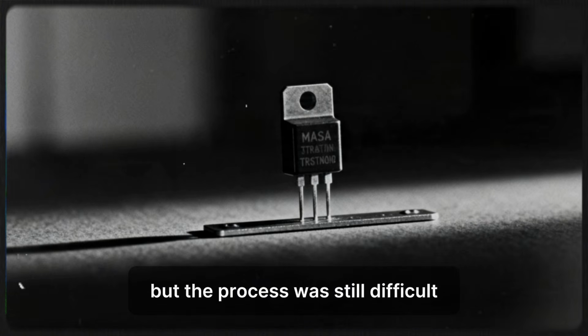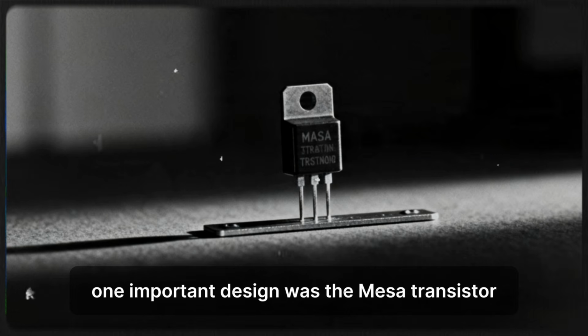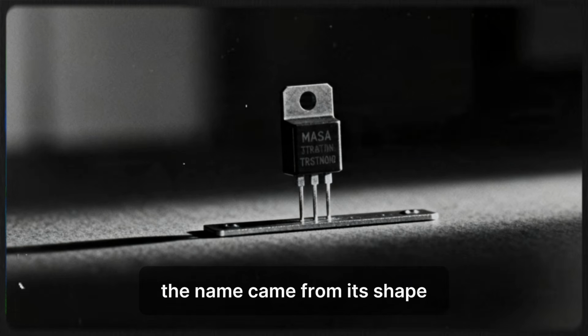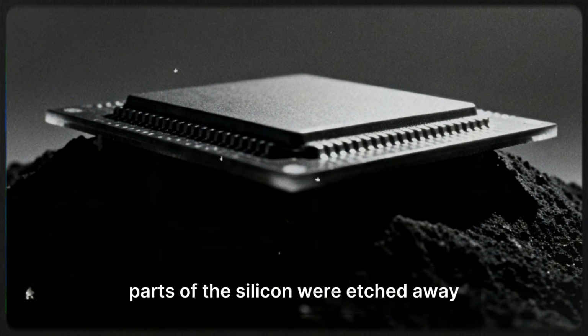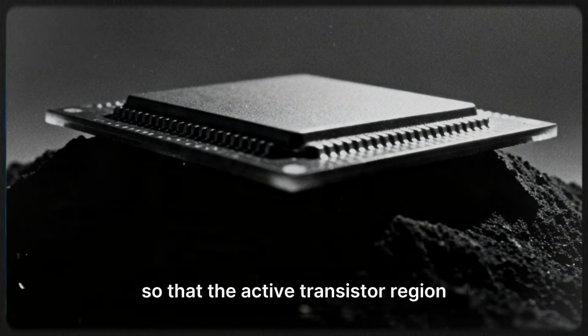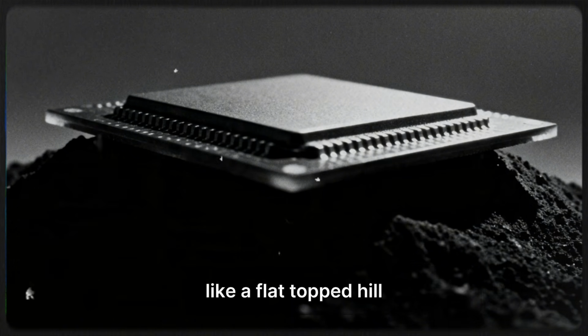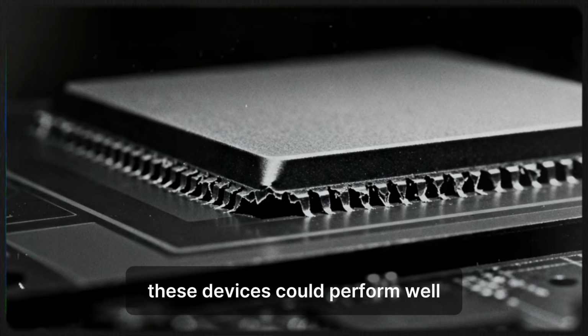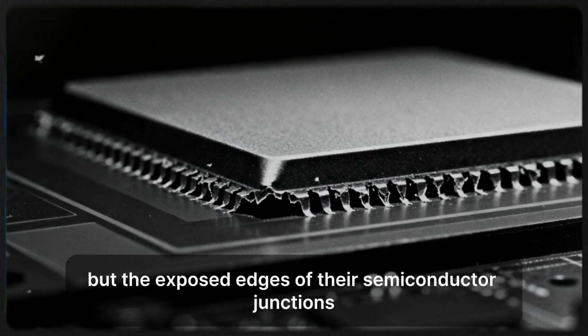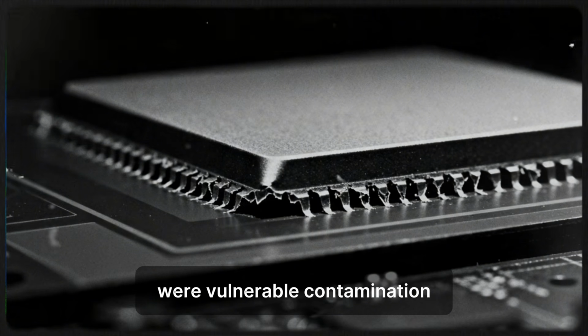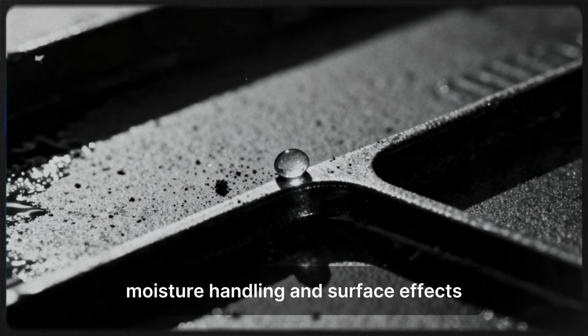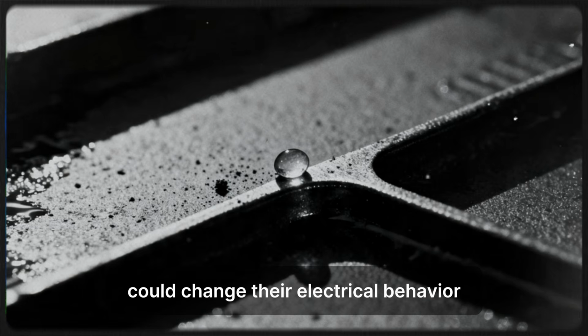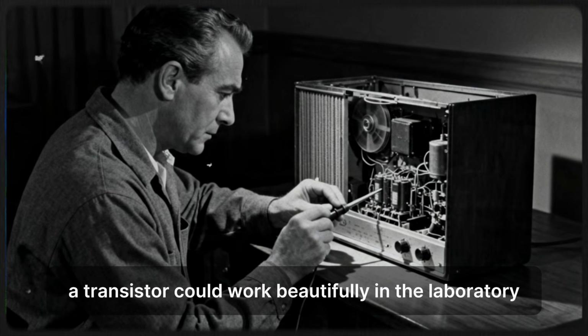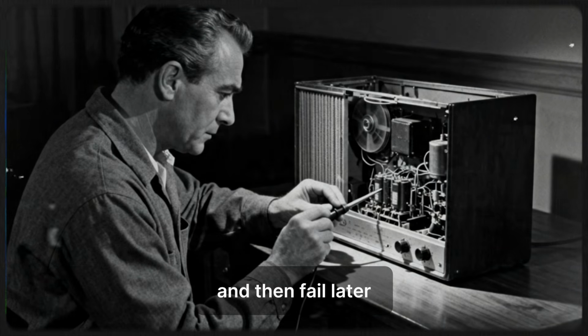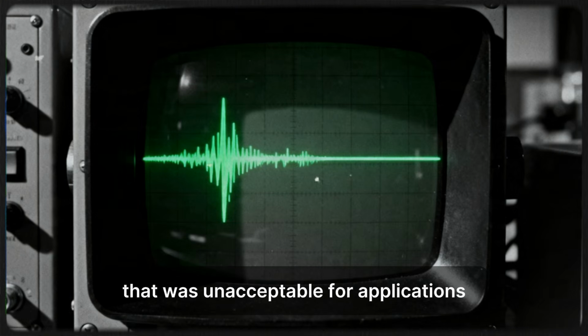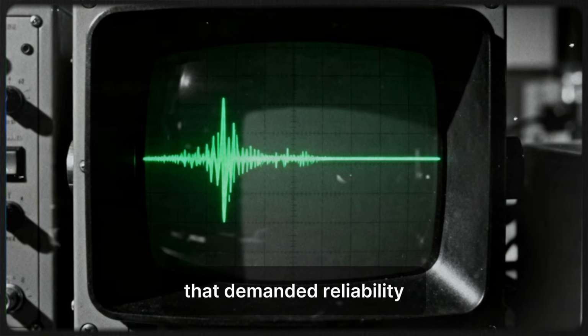But the process was still difficult. One important design was the Mesa transistor. The name came from its shape. Parts of the silicon were etched away so that the active transistor region stood above the surrounding material like a flat-topped hill. These devices could perform well, but the exposed edges of their semiconductor junctions were vulnerable. Contamination, moisture, handling, and surface effects could change their electrical behavior. A transistor could work beautifully in the laboratory and then fail later. That was unacceptable for applications that demanded reliability.